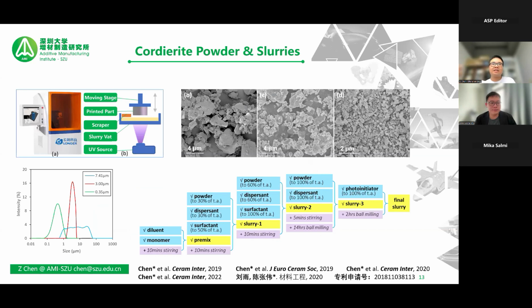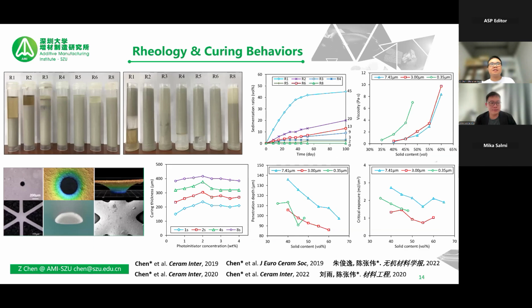After preparing the slurries, we test the sedimentation ratio as well as the viscosity, because these two factors are very important for maintaining a stable slurry. If the slurry is not stable, then during the printing process, after 2 or 3 hours or even 10 hours, the slurry sediments. That can become a problem. So we tried different recipes to see which one is the most stable. Afterwards, we tried the most stable one and saw how well we can print with it. We tried different units, for example, the holes, single lines, and single layers, and tested the curing thickness as well as penetration depth, the critical exposure energy and so on.